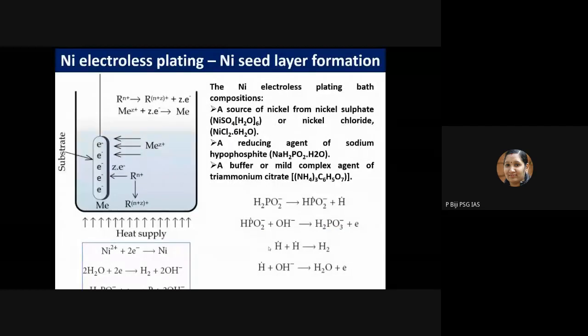Nickel can be deposited using electroless plating, which is very simple. Basically, electroless plating is a kind of autocatalytic process in which the plating can take place on an activated substrate. You need activation of your substrate without the need of electrodes or current flow. Unlike electroplating, you don't have to apply any voltage. Electroless deposition actually involves a reduction of the metal cations by electrons obtained from the reducing agent.